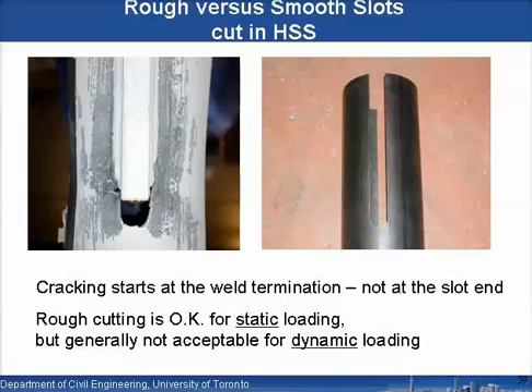Because the cracking will start at the termination of the weld here. The weld transfers the load between the plate and the tube, and so the load is transferred especially at the end of the weld, and so cracking will start at this particular point if the connection fails, and go out here and then tear out down here, or it'll run around the cross section and fracture around the cross section there. So that's the critical point that you have to worry about, and keep the cut quite smooth at that point.